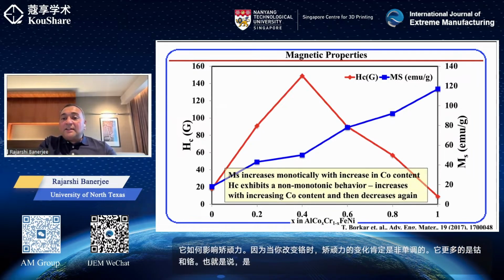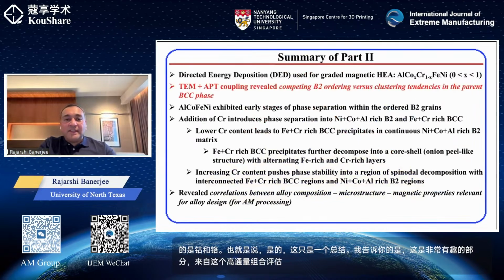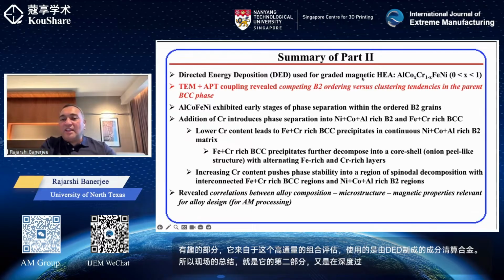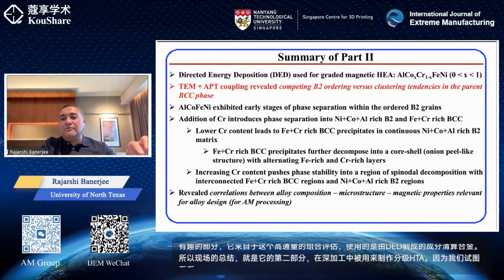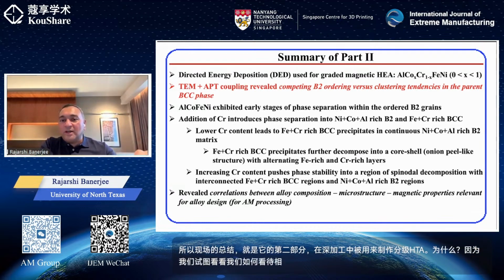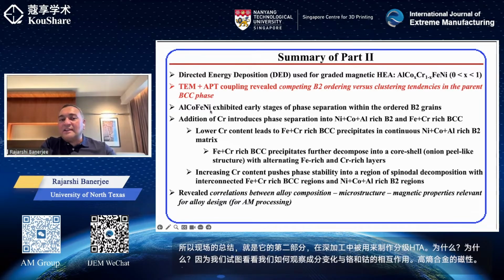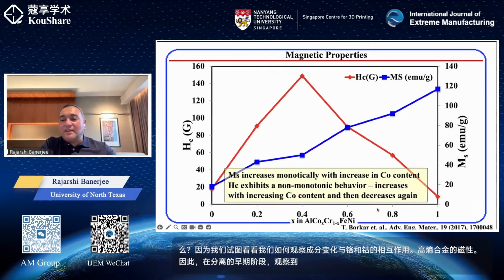This is the part that is very interesting and came out of this high-throughput combinatorial assessment using compositionally graded alloy made with DED. So the summary of this second part is that the DED process was used for making a graded HEA. And why? Because we were trying to look at the interplay of the compositional change with chromium addition to cobalt in the high entropy alloy on the magnetic properties. So in the AlCoFeNi case, very early stages of phase separation were observed, but magnetism-wise it was really nice because of very low coercivity and high saturation magnetization.